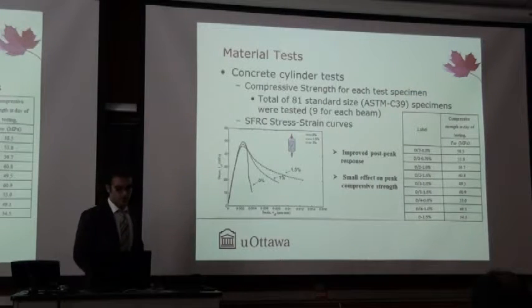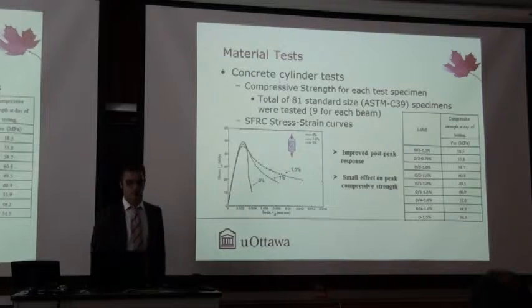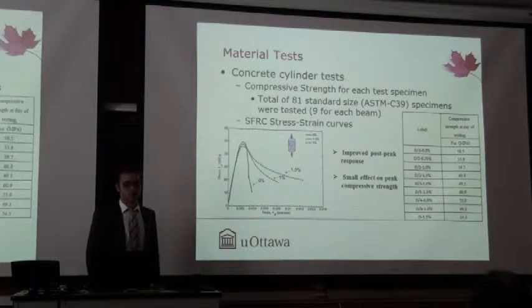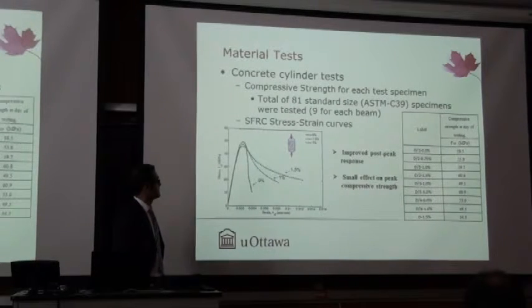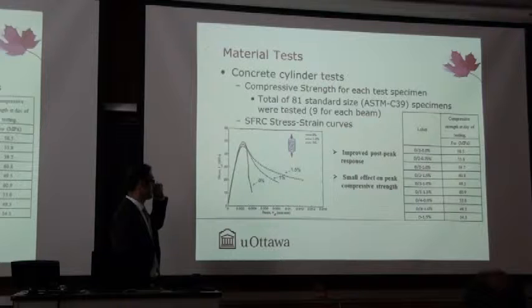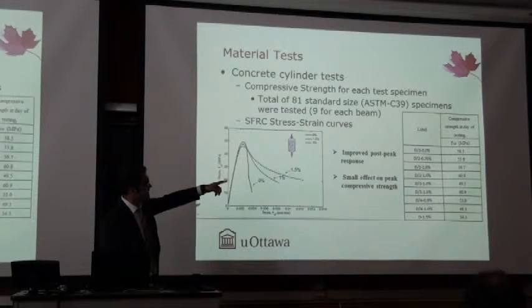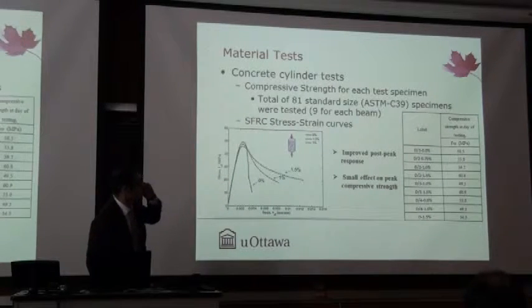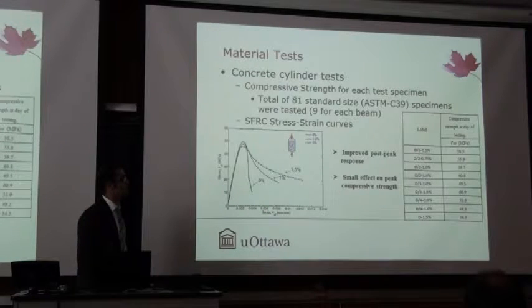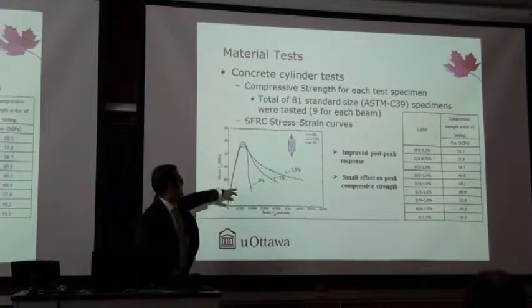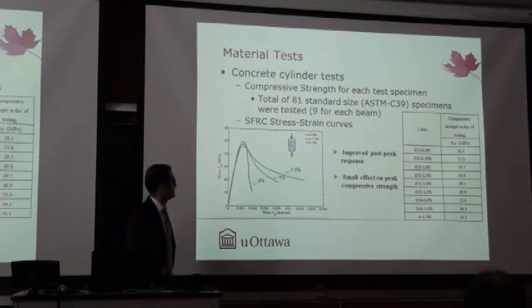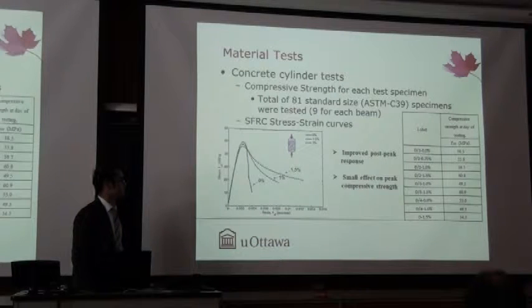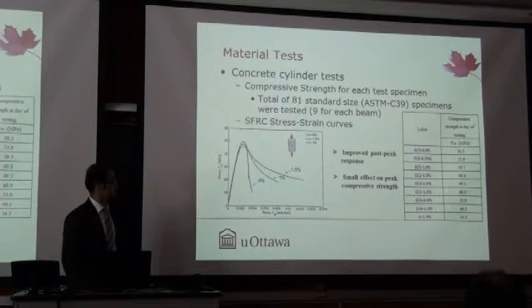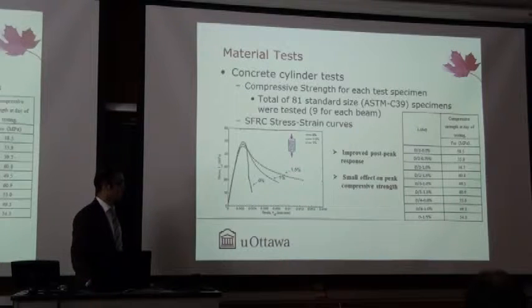We did some material testing. Basically, we did 81 standard size concrete cylinder tests. We also got some full stress-strain diagrams for the concrete tests. You can see in that table the compressive strength for the concrete used in all of my specimens, and also this specification diagram. And you can see the improvement in the post-peak behavior of the SFRC. The most improvement is in concrete with 1.5% steel fibers.